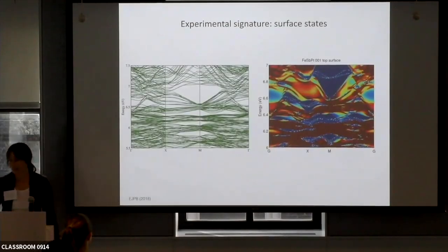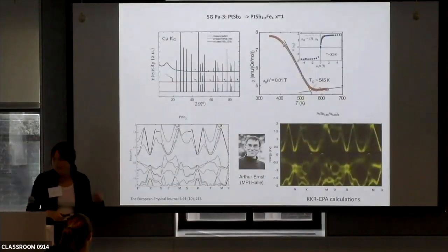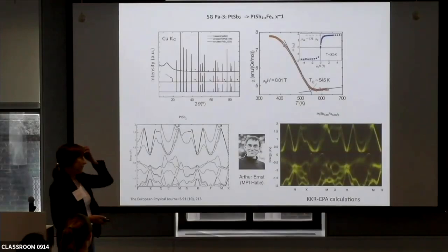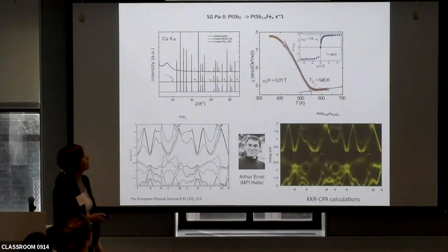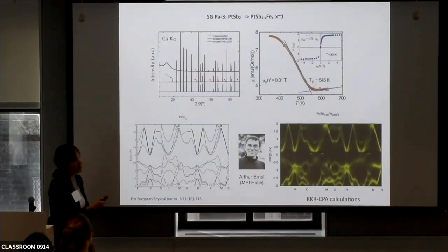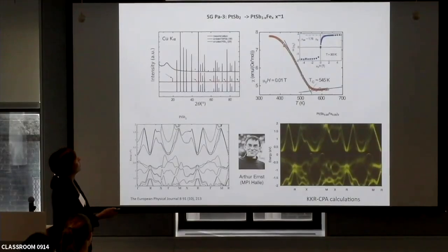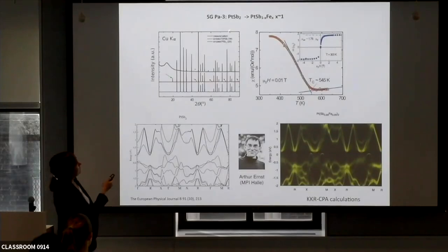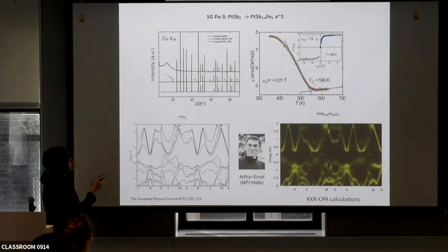However, when they tried to grow this material, it happens that the experimental paper that reported the space group was wrong. So the black line here is the measurement pattern. The red one here is the simulated intensity for PtSb2 in the space group we wanted, and the blue one is what they measured.